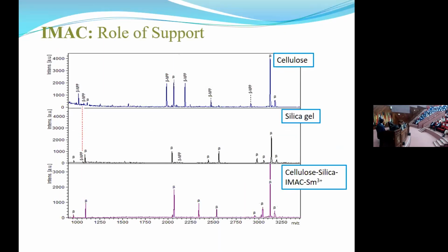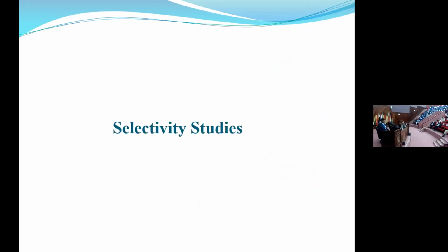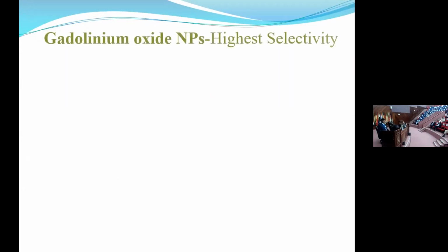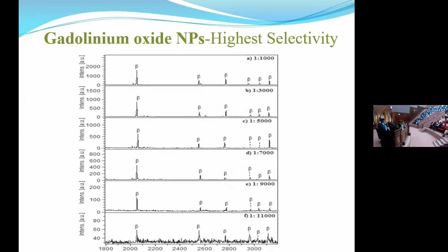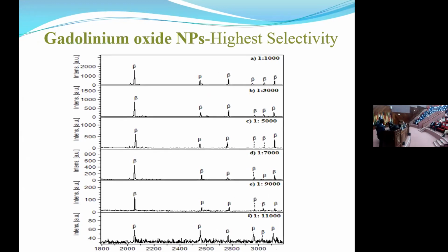And when you use the material in the individual form and then you make the composite, results will also vary. Like here in this case, cellulose, silica, and when you make a composite and then you load with the metal ion, you will get different results. As I said, the selectivity study for 1 to 11,000 was obtained from this material, gadolinium oxide. As I said, this is the highest ever selectivity reported in the field of separation science, and this is the proof of concept given here.